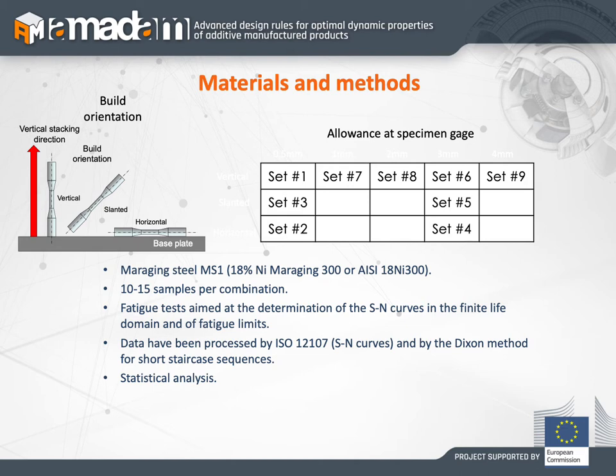In a previous study, we considered three orientations of the specimen inside the chamber. As you can see, vertical, slanted, horizontal, depending on the direction of construction. The vertical direction of the disposition of the layers is the most common, but we wanted to understand if the different orientation in the chamber could have an effect on the fatigue results. And then we considered also the allowance in the specimen gauge before the machining operation. Therefore you can see here that we consider nine different sets of specimens in the plan of experimental tests.